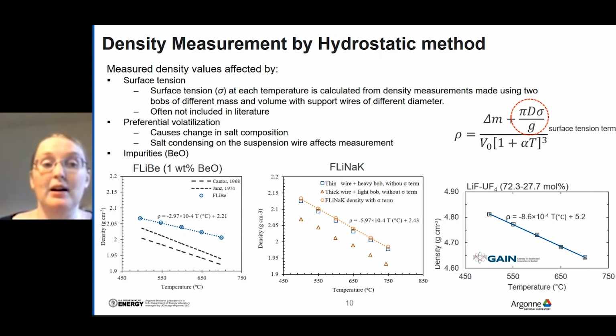And then lastly are impurities. So particularly beryllium oxide seems to have a large effect. You can see in the figure on the left, we measured FLiBe with a known 1 weight % concentration of beryllium oxide contaminant, and our data, while very precise, differs significantly from that in the literature. But also the literature values differ significantly. So it's clear that beryllium oxide contamination, which is hard to get away from with FLiBe, can be an ongoing issue, and impurities in general can be an issue we need to quantify. So when reporting salt data, it's really important to be measuring and reporting those impurity levels.